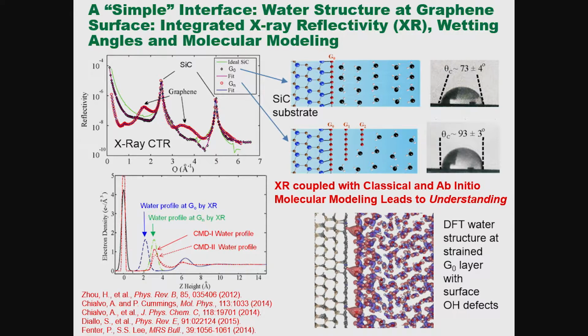The guys also did contact wetting angle measurements of how water sees a single graphene layer on the surface versus multiple graphene layers. What's clear is that this first layer of graphene is very different from bulk graphite or multi-layer graphene, in the sense that it's much more hydrophilic and also exhibits different behavior.